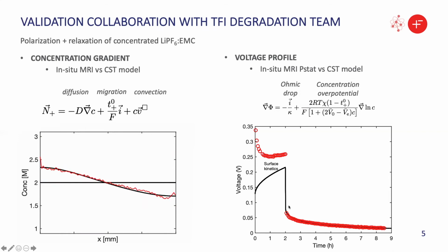And so you can see during that relaxation step, we can validate our parameters between the experiment and model. And what's quite interesting is that if you know everything in the bulk, you can actually accurately extract out the surface kinetic overpotentials, which will be useful for understanding lithium metal and other interfacial phenomena.